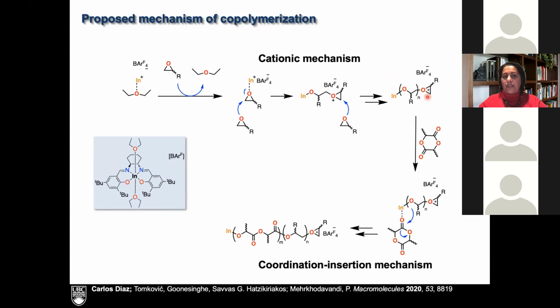And then what Carlos was able to show is that in this situation, once this polymerization is complete, lactide starts polymerizing on this end. So lactide isn't polymerized cationically under these conditions, it's polymerized via a coordination insertion mechanism. So you can have lactide polymerization here while having cationic epoxide polymerization here. That's why you have a block copolymer system.